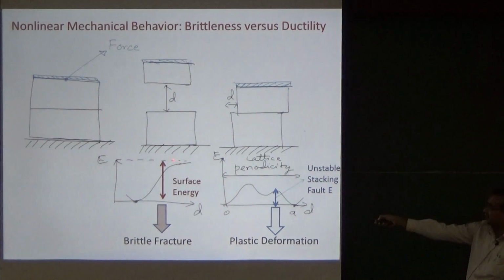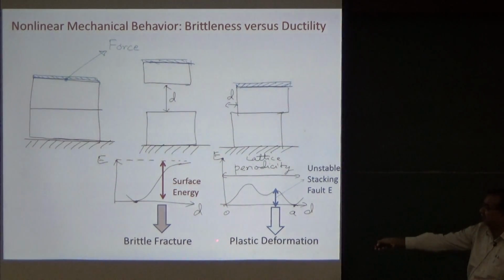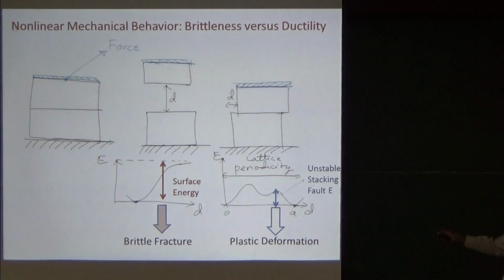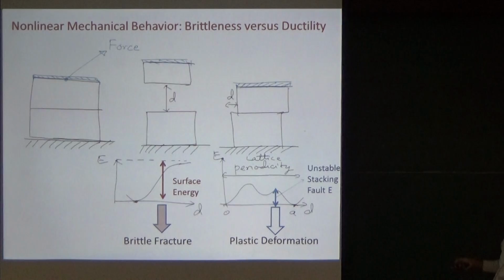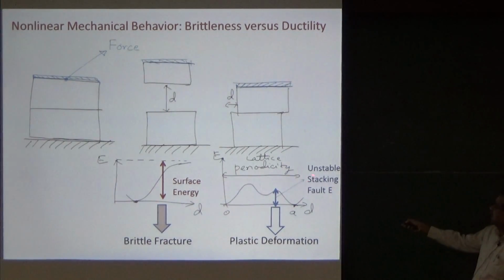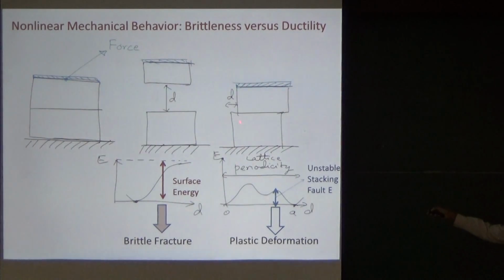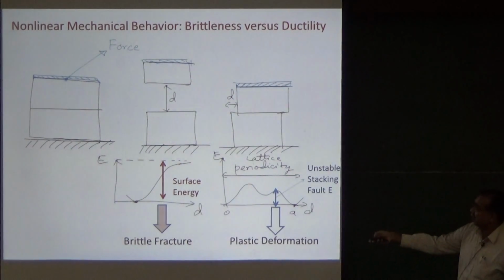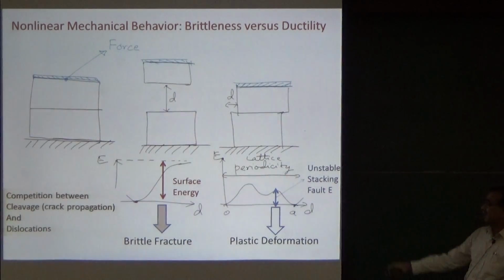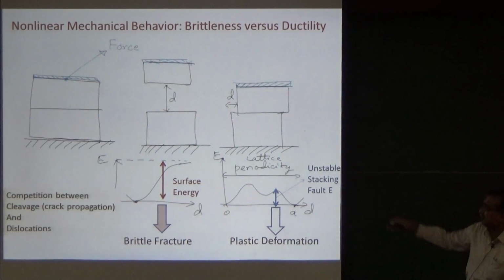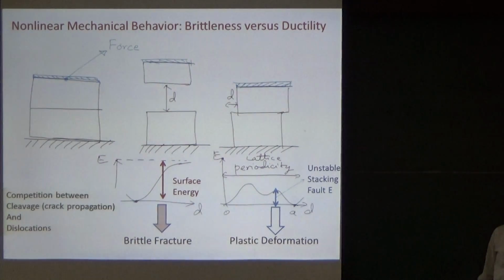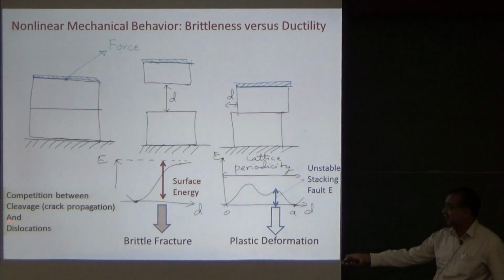So in this case, basically it's the surface energy that is relevant, and that gives you brittle fracture, or rather what is called crack propagation. And in this case, you basically get a slip mechanism which gives an energy surface which has the periodicity of the lattice as shown here. And the energy barriers that you get along these slips basically control what is called the unstable stacking fault energy, which controls the nucleation of dislocation in a material. So ductility is caused by dislocations nucleating and also moving, and brittleness is caused by basically crack propagation. Okay, and crack propagation is described by cleavage energy or surface energy. So this behavior of a material typically involves competition between crack propagation and dislocation mechanism.